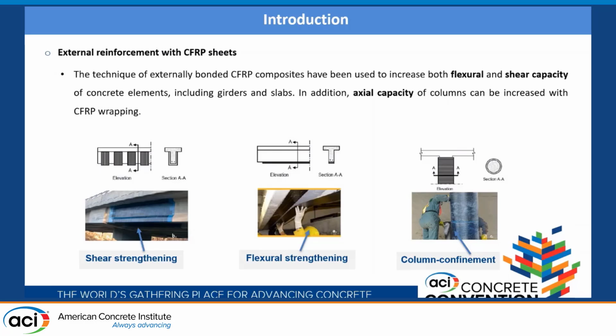The technique of externally bonded CFRP composites has been used to increase both flexural and shear capacity of concrete elements, including girders and slabs. In addition, axial capacity of columns can be increased with CFRP wrapping. For shear strengthening, CFRPs are bonded to the lateral face of concrete beams. For flexural strengthening, CFRP are bonded on the tension side. The fibers are oriented in the longitudinal direction to increase flexural properties. And for axial strengthening, CFRP encircle the structure and prevent concrete expansion under compressive load.